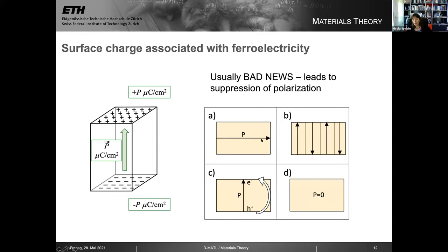So for example, the polarization might go in plane, right? Because if I have a film and my polarization is in plane, then I don't have any surface charge on the surface. The polarization might split up into domains, because then I have only a little bit of positive charge here and then immediately some negative charge. So averaged over this whole surface, I don't have much net charge. The system might spontaneously generate electron hole pairs to compensate the charge. It might make excitations of electron hole pairs across the gap, so the electrons can come and sit on the positive surface and screen and neutralize the surface charge. The holes can go to the bottom surface. And it can even make a phase transition to a state that doesn't have any polarization. So it can stabilize the paraelectric state, or maybe even make a completely new phase that's actually non-polar. And I want to start by showing you an example of this last case, because it's a really beautiful example, I think, of where density functional theory calculations were able to contribute to understanding this topic.